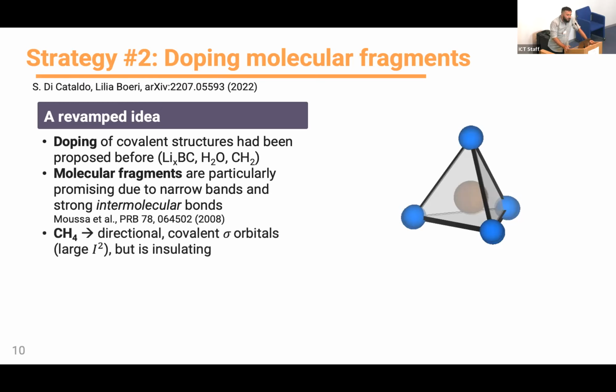Now, what's the problem in this strategy? Let me illustrate that with an example. Here on the right, I'm showing a picture of methane. It's a tetrahedral structure with carbon in the middle. It's bound to 4 hydrogen atoms, and it has some very strong bonding sigma orbitals, which in principle have a very large electron-phonon matrix element. The problem is that methane is insulating. So if we were to apply pressure, which we don't want, it remains insulating up to extreme pressures.